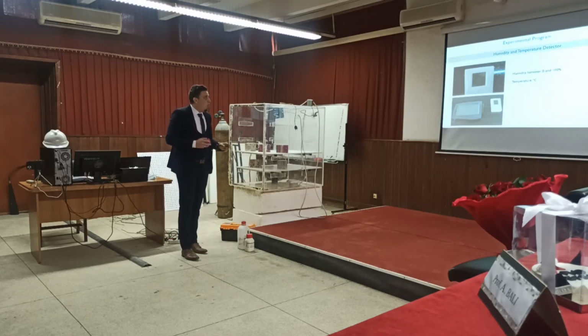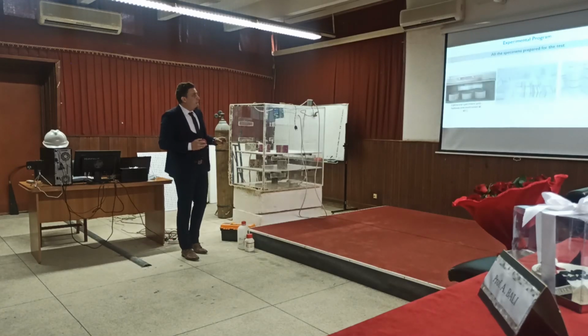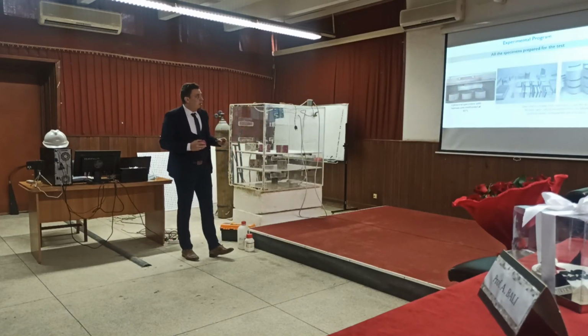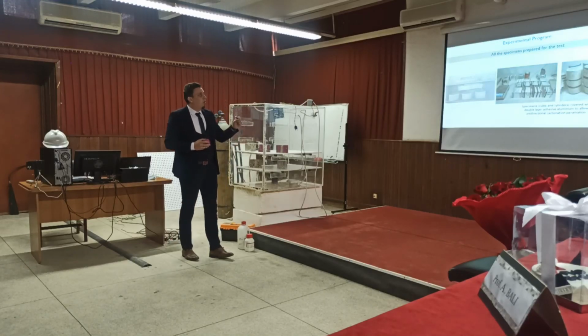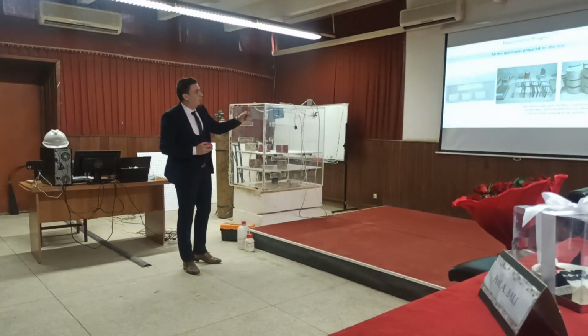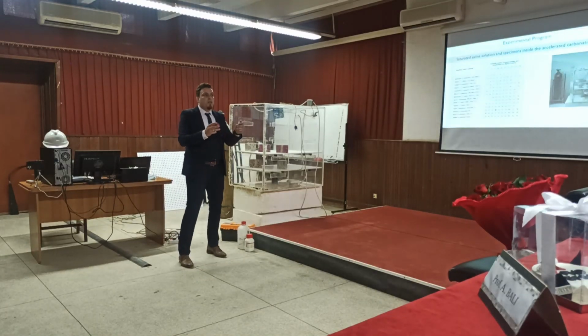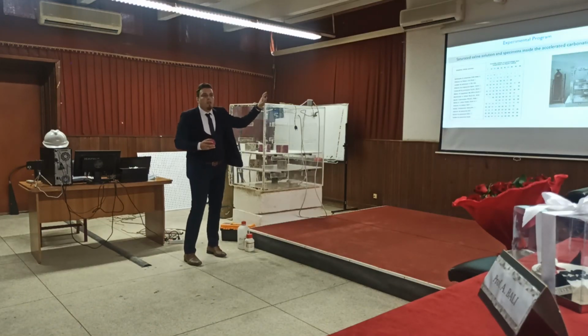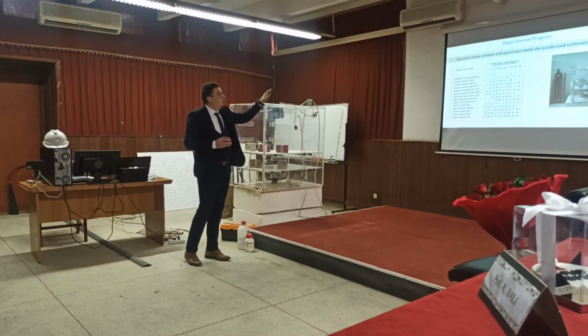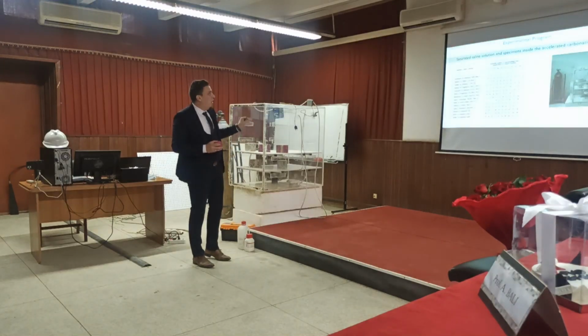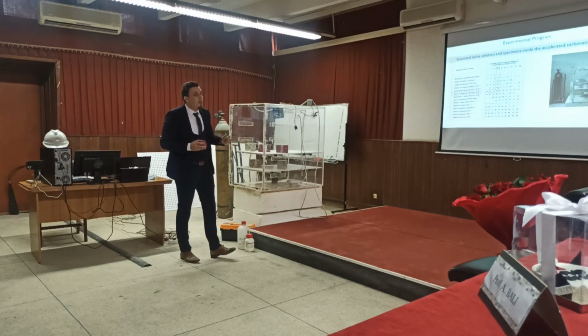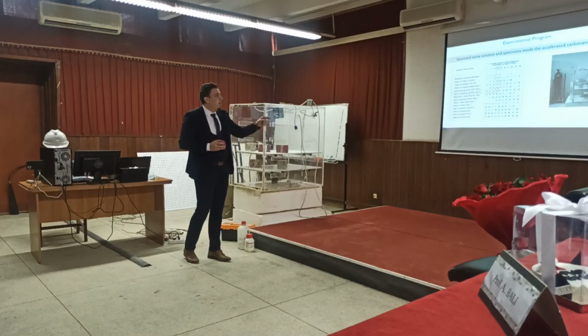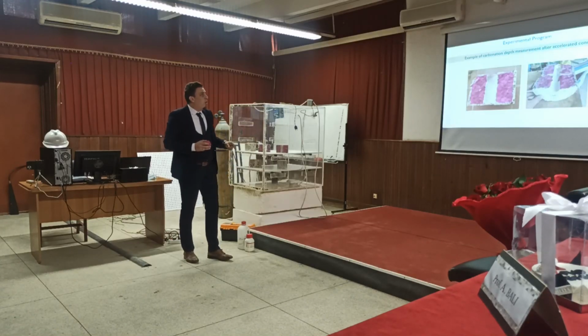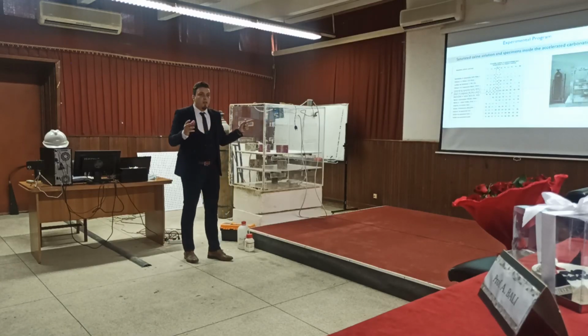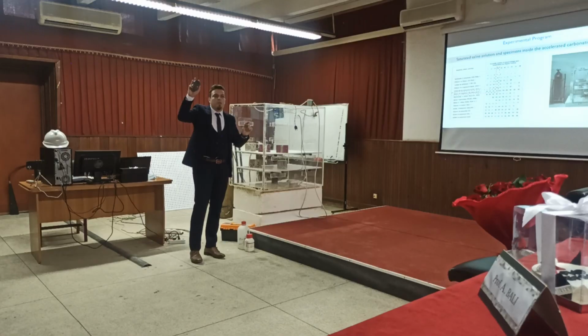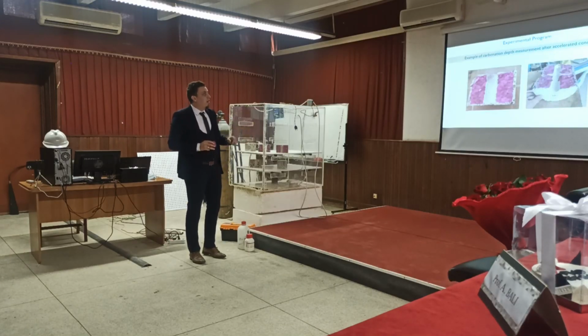After that, all the specimens will be preconditioned and prepared with double layer adhesive aluminum to allow unidirectional carbonation penetration, as you see here. After that, all the specimens will be subjected to accelerated conditions. But here I should mention that we should ensure the humidity. We use saturated saline solutions, and we work with magnesium nitrate that generates 55% humidity, as you see here. After that, we assess again all the characteristics: the oxygen permeability, the compressive strength, the weight variation, besides the carbonation depth.